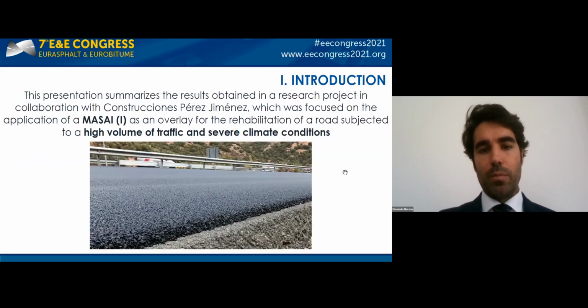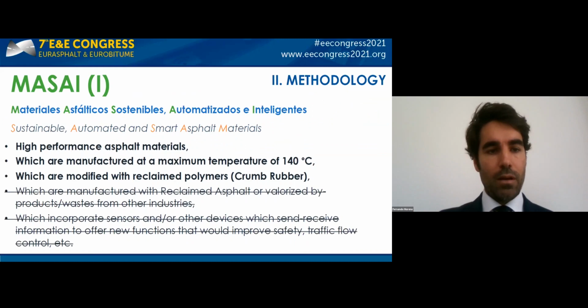This presentation summarizes the results obtained in a research project in collaboration with Construcciones Pérez Jiménez, which focused on the application of a MASAI (I) as an overlay for the rehabilitation of a road subjected to a high volume of traffic and severe climate conditions. The MASAI (I) used was a high-performance asphalt material manufactured at a maximum temperature of 140 degrees and with a crumb rubber modified asphalt bitumen.